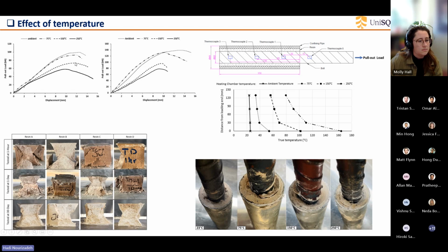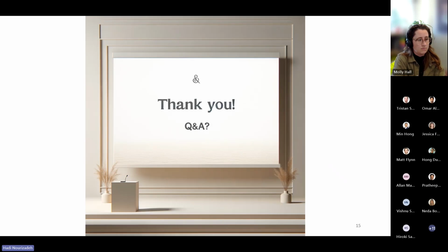For example, in this specific type of resin, the maximum pullout bearing capacity at ambient temperature is around 100. For the other resin it is around 140. When we increase the temperature to 250 degrees Celsius, the pullout capacity decreased to around 60 MPa, and in the other resin it decreased to 80 MPa. All this data shows that we need to consider the effect of temperature and the environmental condition when we design any reinforcing systems. So I think this is the end of my presentation.